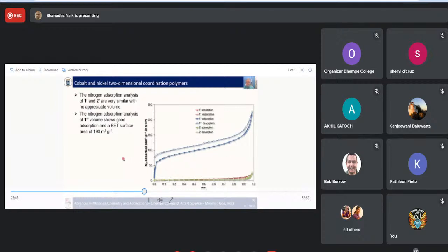The nitrogen adsorption analysis shows that 1 double prime here has a really nice adsorption profile. And so it goes up to about 190 milliliters per gram at STP. Whereas 1 prime and 2 prime have absolutely no adsorption whatsoever. They're basically the same as just a powder. So this is very interesting, and we actually want to characterize this number 1 prime with 1 double prime a bit better, because it's an amorphous compound. It's really difficult to analyze.